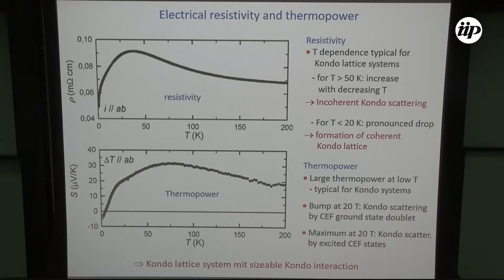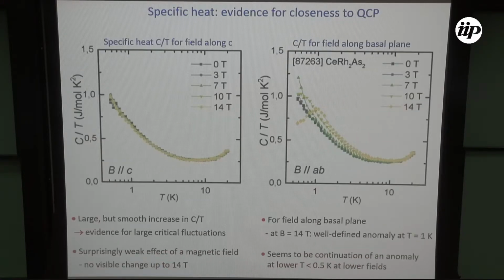The next test is to do the thermopower. In a normal metal, the 4f electrons are completely localized, they do not interact, and therefore they do not contribute to the thermopower. You get a very small thermopower with a weak temperature dependence. In this case, you get a very large thermopower, which reflects the strong scattering of the conduction electrons by the 4f states, and the temperature dependence is also quite typical for such a system. You have a bump here, which is likely associated with the Kondo scale, and a broad maximum here, which is likely associated with excitation of the excited crystal field state at higher energy. So from that, we can already say that we have a Kondo lattice system with a sizable Kondo interaction.